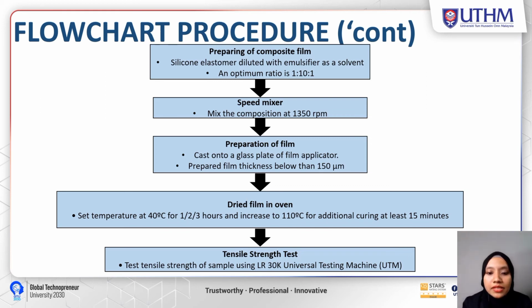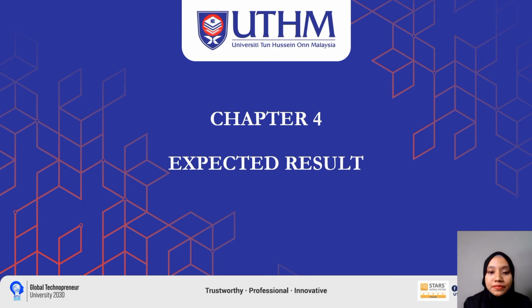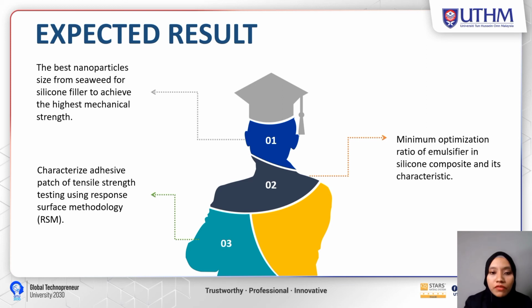And step 10, tensile strength test. Test the tensile strength of the sample using the LR30K Universal Testing Machine, UTM. And next is Chapter 4, expected result. The expected result for my project FYP is the best nanoparticle size from the seaweed for silicone filler to achieve the highest mechanical strength. Then characterize the adhesive patch by tensile strength testing using response surface methodology, RSM. And then get the minimum optimization ratio of the emulsifier in the silicone composite and its characteristics.